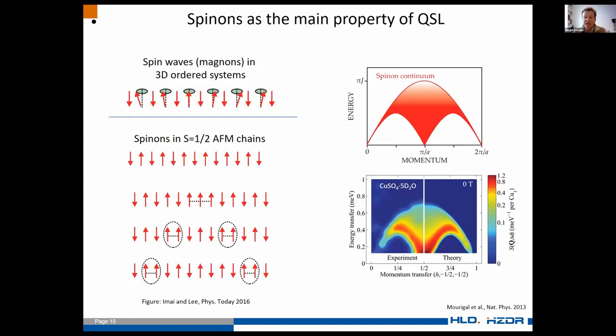As I said, the largest difference is between spin waves and spinons, although if you look at the excitation spectrum using inelastic neutron scattering, you would see something similar. But in the case of spinons, we would see quite a big difference in the intensity of scattering, and this is what makes this observation so different. We can describe the spin waves using a classical approach, but for the spinon continuum we should use quantum mechanical language. This model was solved a long time ago using Bethe ansatz. At least we know what to expect for quantum spin liquids: some sort of continuum, and this is what we are looking for.